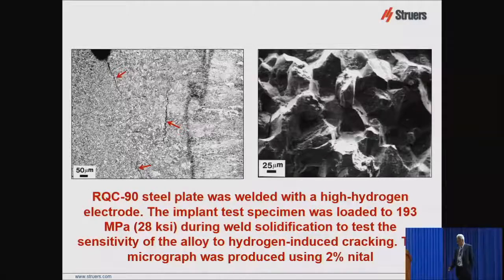Here's the fracture surface. It's predominantly intergranular. This etch was Nital. And you can see there's cracks here, crack over here. And this is part of the fracture surface up here. And of course, that's not a good performance.